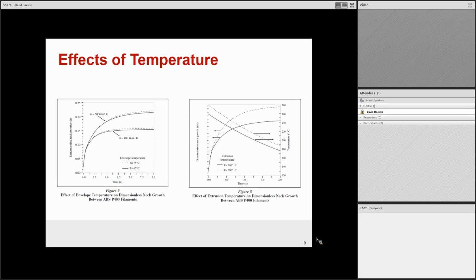And they were able to determine that in figure 8, the dotted line is much higher than the straight line, showing that the neck growth is higher, and the extrusion temperature has a greater effect on the neck growth. You see two sets of lines on figure 8. The second set of lines that are sloping downwards is the cooling process for the filament. Another note that they made is that even though you get better performance at higher temperatures, you will eventually start degrading the bonds between the ABS plastic. Again, this adds to the need to find experimental data to optimize the extrusion temperature for the maximum strength in your parts.